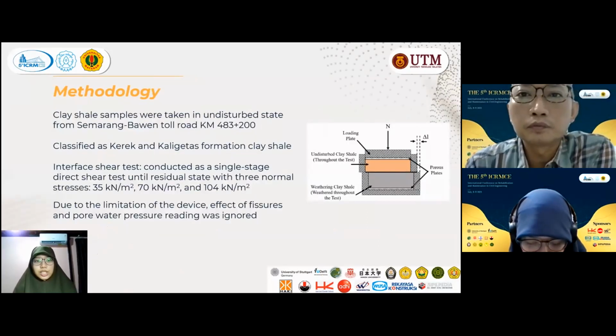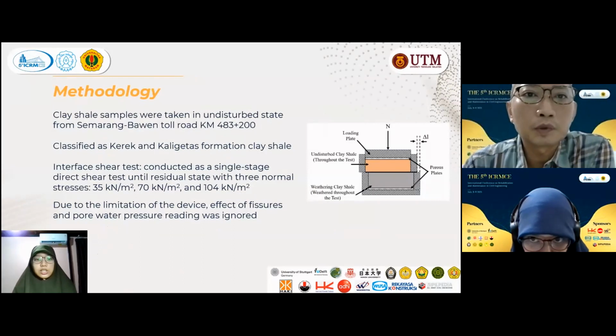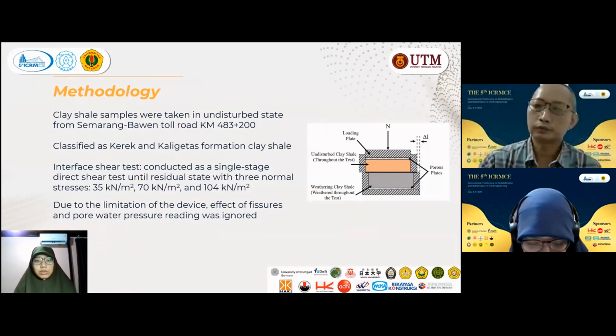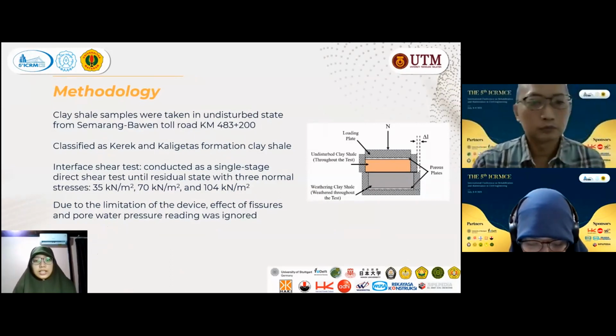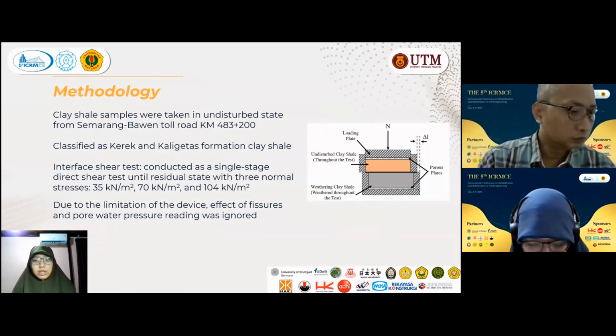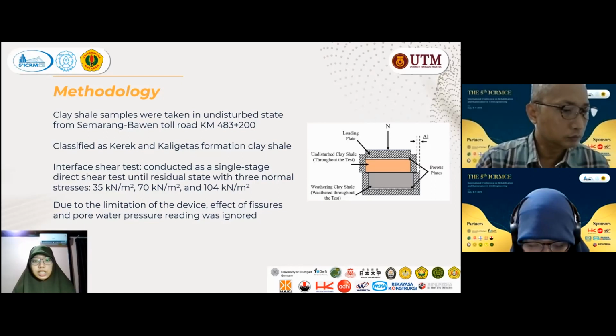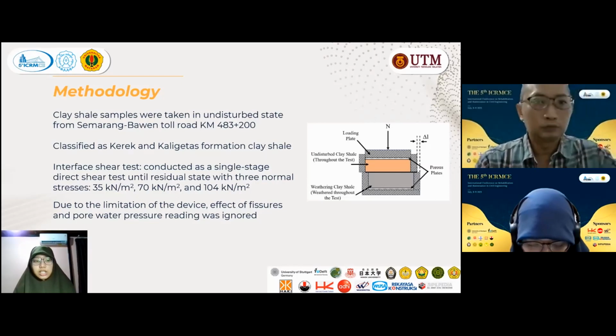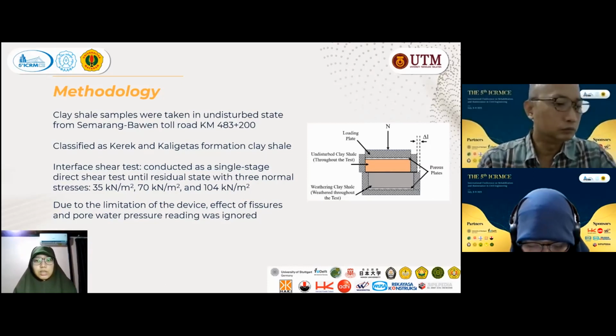So, clay shale samples were taken in undisturbed state from Semarang-Bawen toll road, kilometer 483 plus 200. It is classified as Kerek and Kaligetas Formation clay shale. The interface shear test was conducted as a single-stage direct shear test until its residual state with 3 normal stresses of 35, 70, and 104 kN per square meter. The undisturbed clay shale was cut into 2 pieces for the upper part of the shear box and the lower part of the shear box, with the upper part being the undisturbed clay shale and the lower part the weathered clay shale. Due to the limitation of the device, the effect of fissures and pore water pressure reading was ignored.